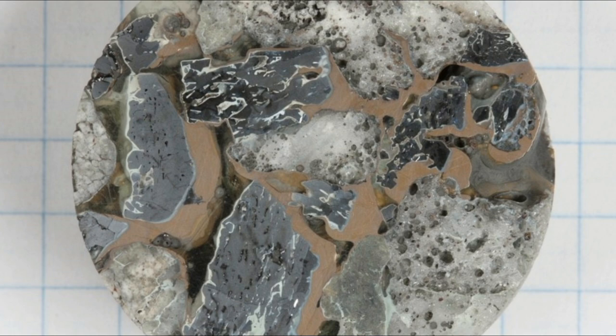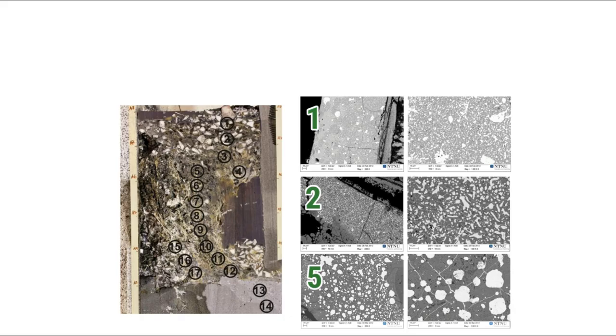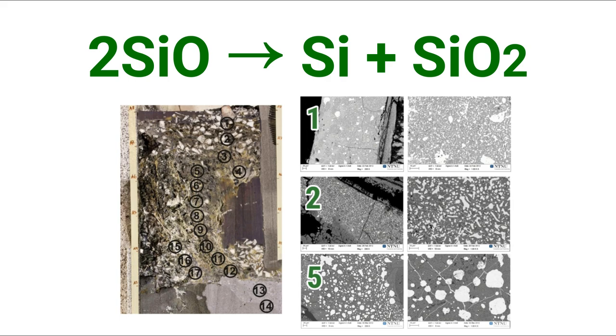The brown condensate will agglomerate the quartz and the silicon carbide particles as shown in the picture. Micrographs of this brown condensate show that it is silicon embedded in a silicon dioxide matrix. When this condensate is heated as it descends with the raw materials, the silicon will accumulate into larger silicon drops, and then finally, at high enough temperatures where both silicon dioxide and silicon are melted, the silicon will flow out of the silicon dioxide matrix. As the condensates prevent the materials going down in the furnace, the materials are mechanically pushed down with a stoking machine.